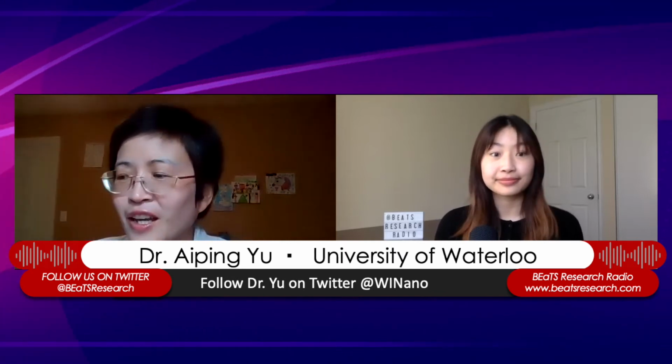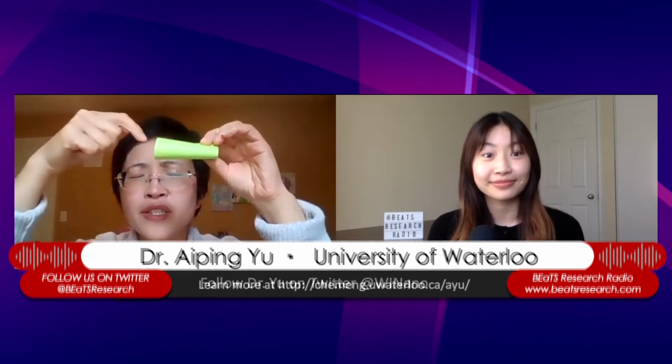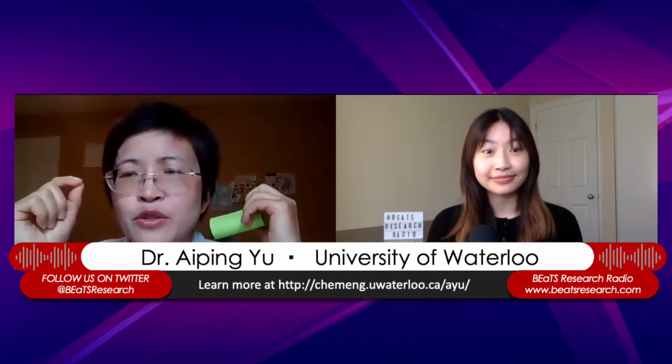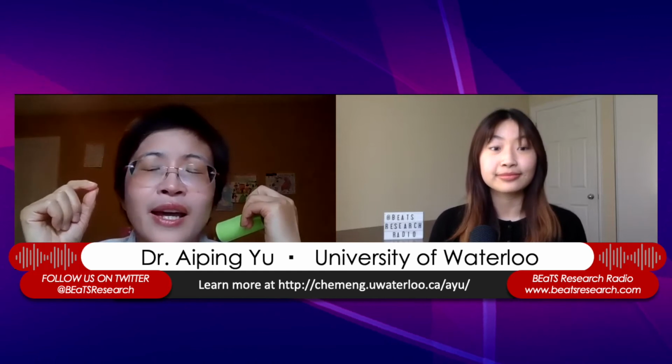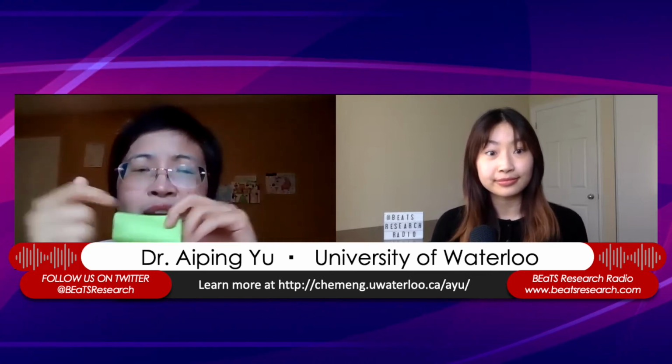But I mentioned it always has defects. The wall has many pores because when you produce the nanotube, naturally you have to use a catalyst. Catalyst is a tiny metal particle. After producing the nanotube, you have to remove this particle. When you remove it, naturally you leave lots of pores. These pores we call defects. Defects reduce the mechanical strength of carbon nanotube, and the reduction is quite significant, at least 50%.